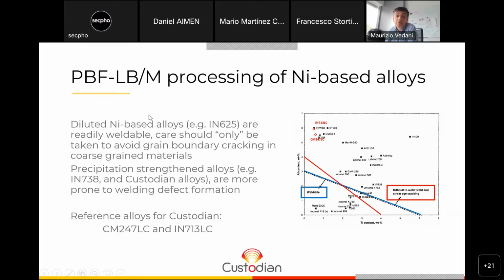So all in all, the most diluted, less alloyed nickel-based materials are readily weldable, while the more highly alloyed, precipitation strengthening materials are more critical in this sense. And this is also the case for the 2 reference materials that have been selected for the custodian investigation, namely the CM247L low carbon alloy and the Inconel 713LC alloy. They are labeled here with red labels, and they are definitely in the difficult to weld region.